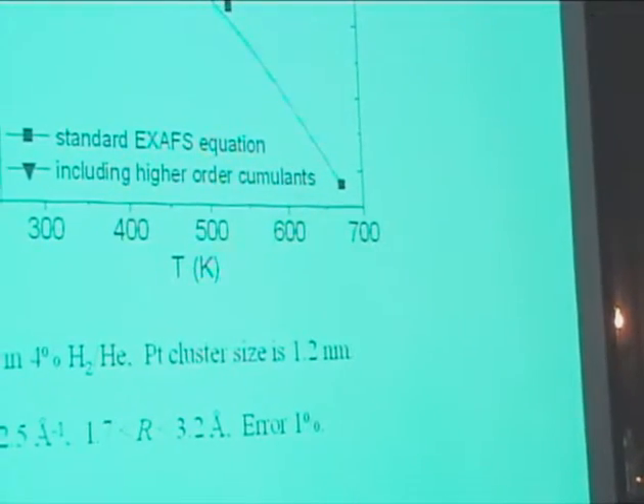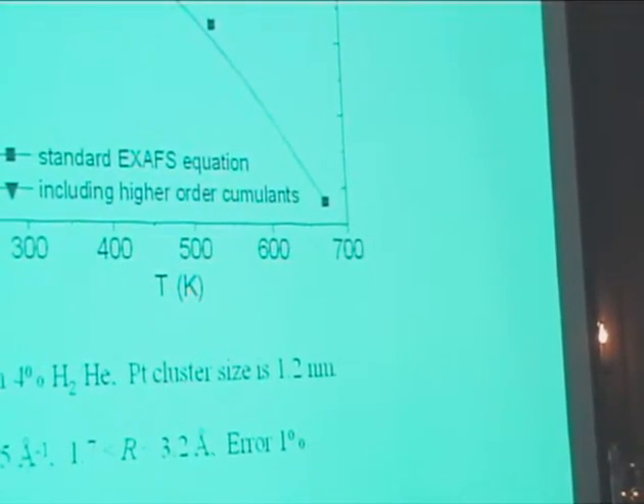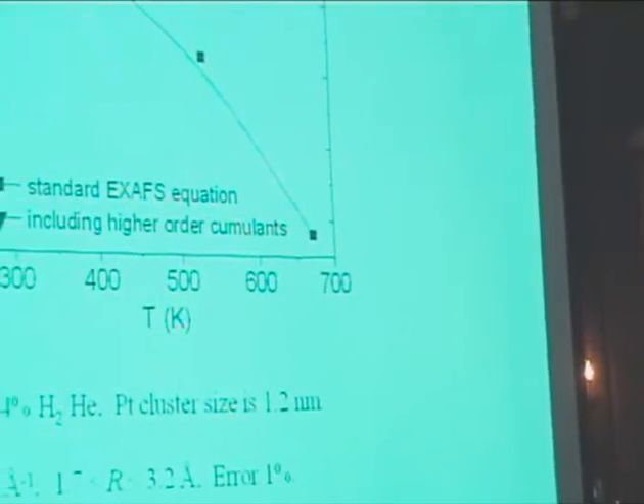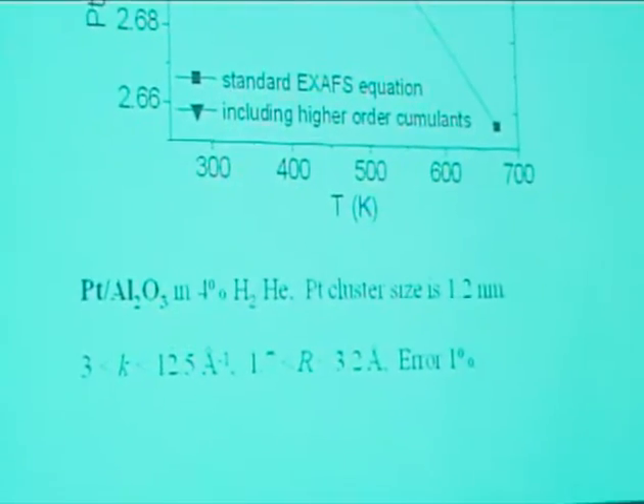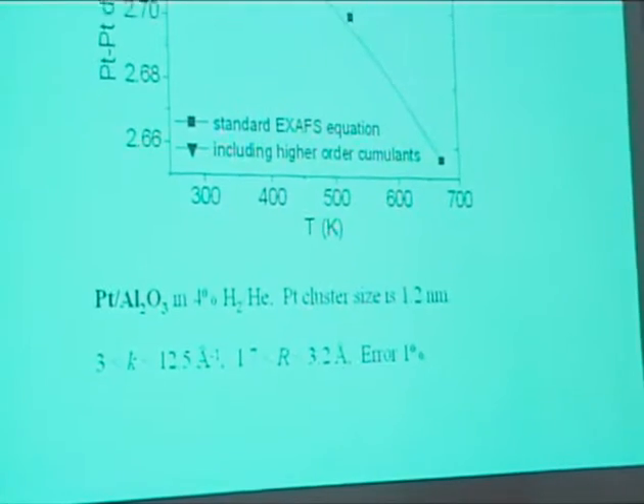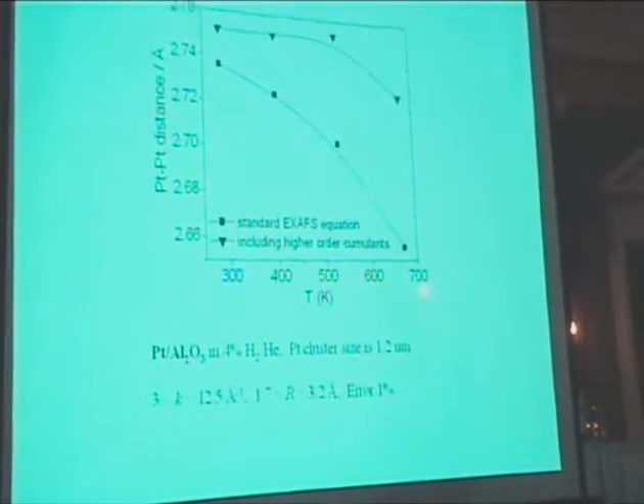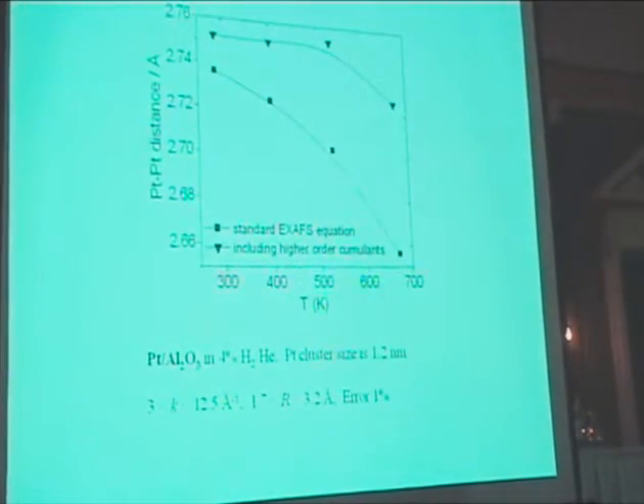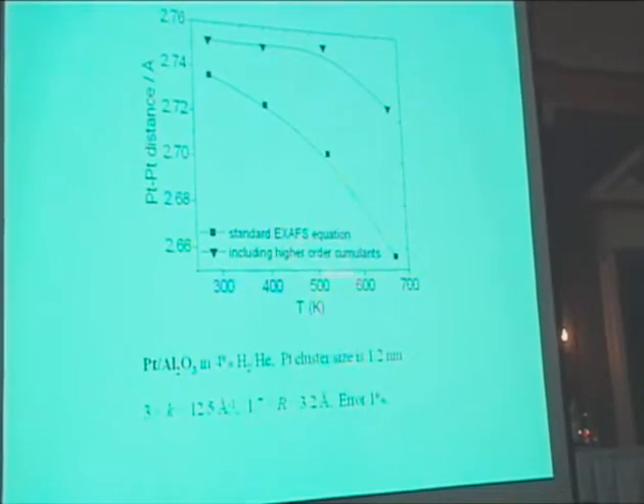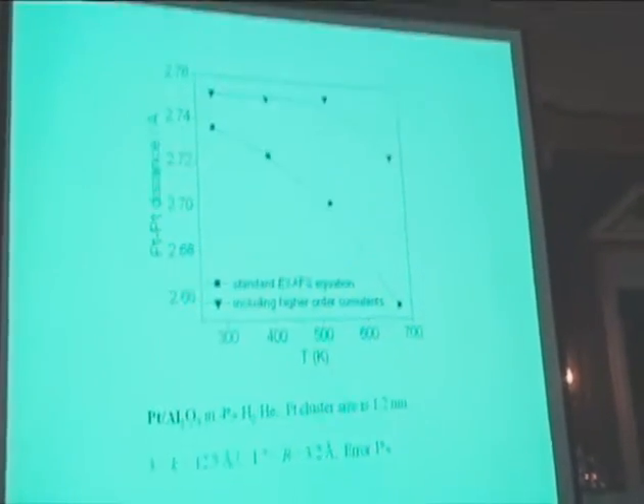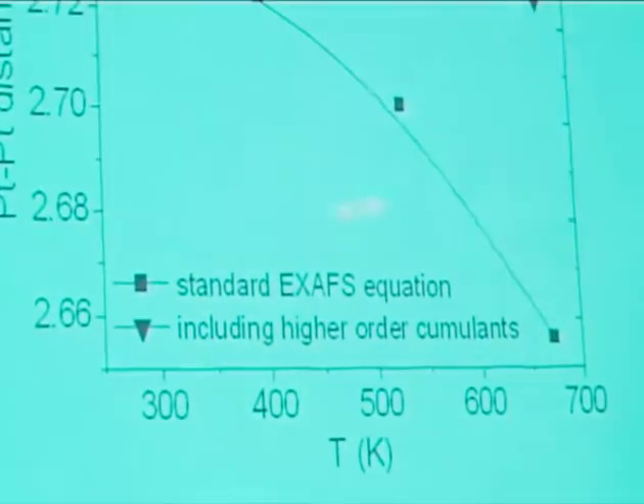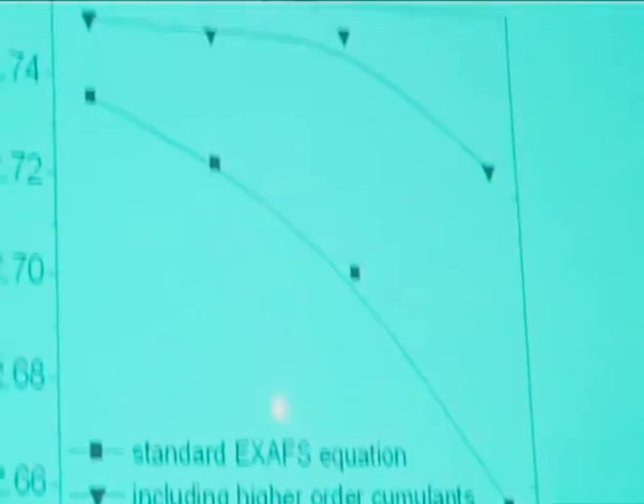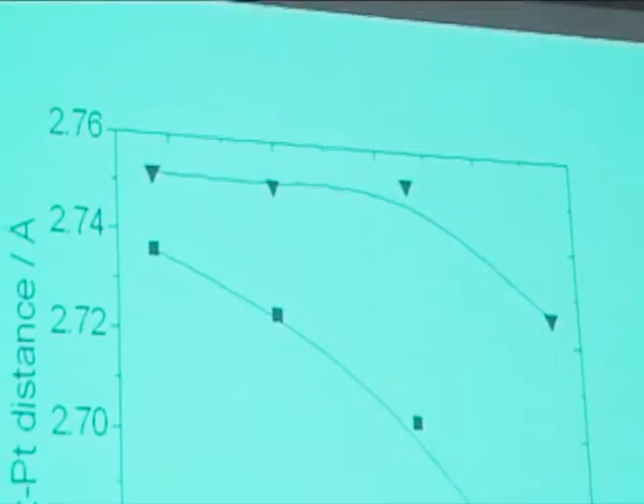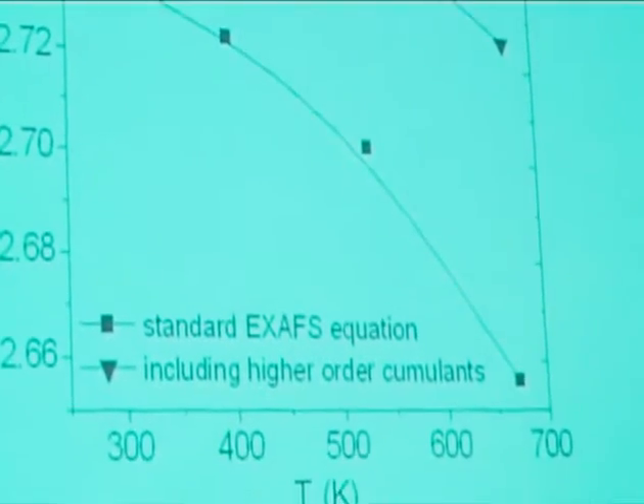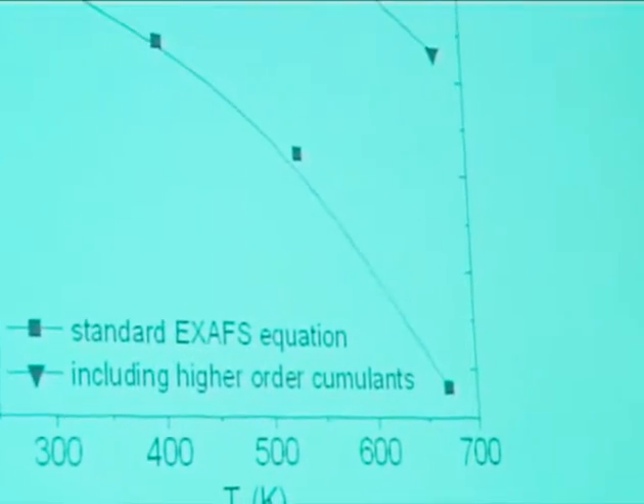Also the distance shows there is something wrong when we look at the platinum distance without the higher cumulants. As a function of temperature, the distance goes from 2.74, it dives, which is against physics. When you go up in temperature, you would expect that because of the Debye-Waller factor you would average over a higher distance, and you have to go up. So this is nonsense. There must be something wrong. So the analysis is wrong because you didn't include the higher order cumulants. If you do that, it's flat.